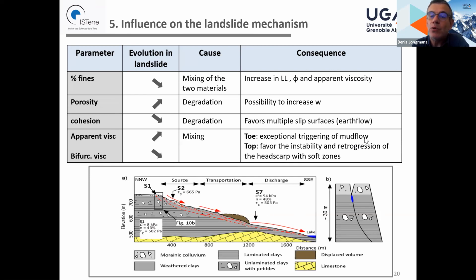Exceptionally, we may have mud flow like the 1981 event. And at the top, in contrast, the thixotropy of the clay may favor the instability and retrogression of the escarp. So I have a little sketch here showing that when you have some fracture behind the escarp, which is here, so rear fractures, which are open in the morainic cover, you may have infiltration of water, and that means that we may reach the critical stress here at some point and cause a liquefaction, a fluidization, more exactly, of the clay, which favors the instability of the escarp.